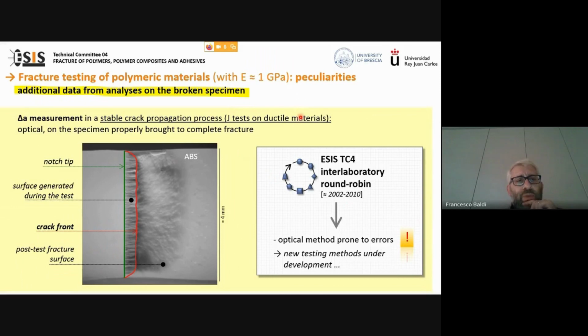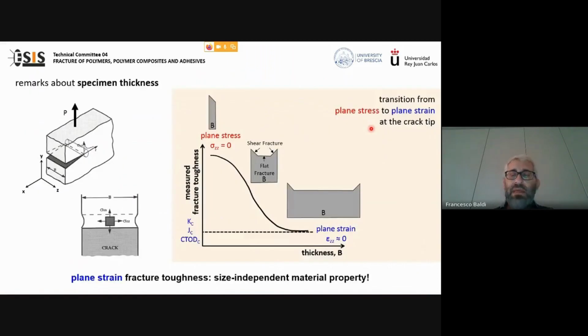Another problem we have to face when we deal with polymers is that the measurement of the crack advancement in a stable crack propagation test, which is optical and is made on a specimen properly brought to complete fracture, is not easy, in the sense that the crack front, which divides the fracture area produced during the fracture test from the remaining area obtained during the complete breakage of the specimen, cannot be easily identified. In fact, some techniques which are not based on the crack advancement measurement are under consideration in our ESIS TC4 table. Another aspect that I would like to remark concerns specimen thickness.